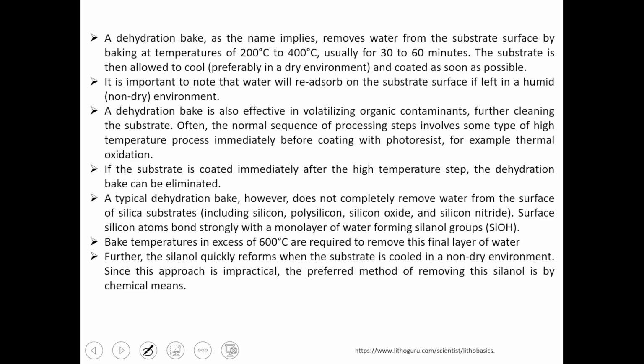A bake temperature in excess of 300 to 600 degrees is required to remove the final layer. Either you do the plasma etch, or you increase the bake temperature to around 600 degrees Celsius, or if required up to 800 degrees Celsius. Further, the silanol quickly reforms when the substrate cools in a non-dry environment. Since this approach is impractical, the preferred method of removing the silanol is by chemical means, either plasma etching or some chemical. Either heat in ethanol, methanol or acetone, or sonicate your substrate in isopropyl alcohol. Okay.